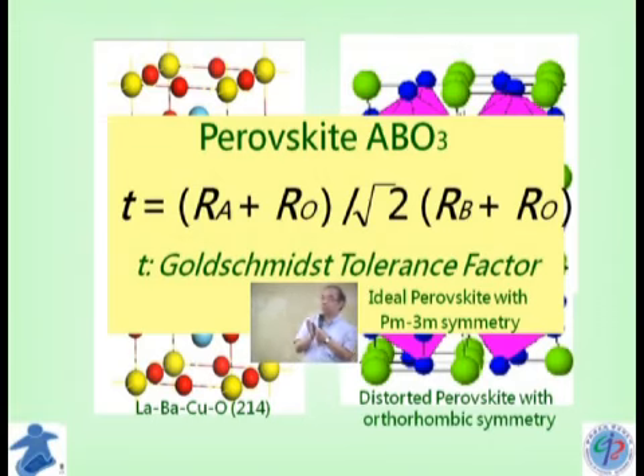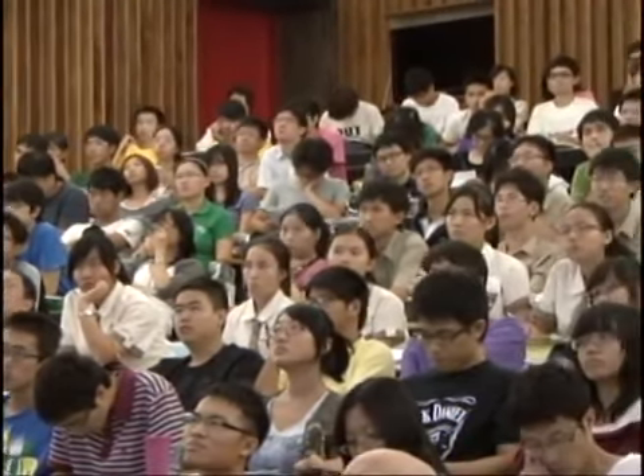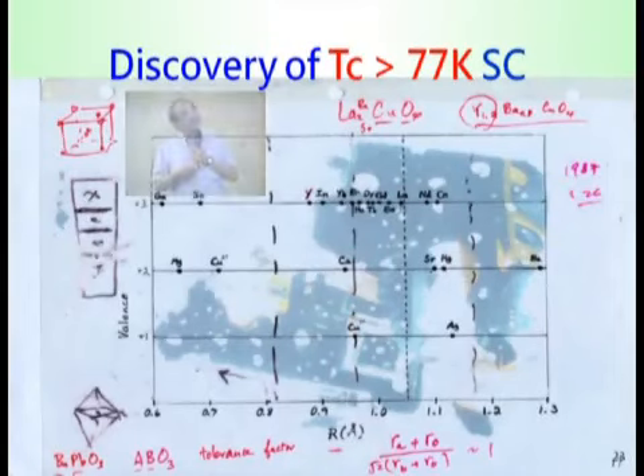The other thing is that, because of the result by Professor Chu showing that as pressure goes up, the TC increases and then comes down, there is some optimal value you want to achieve in terms of the size of the ion. But without going into detail, during the course, my student and I developed this, you see, this original chart. We have put down something; we have tried many elements, we placed them.